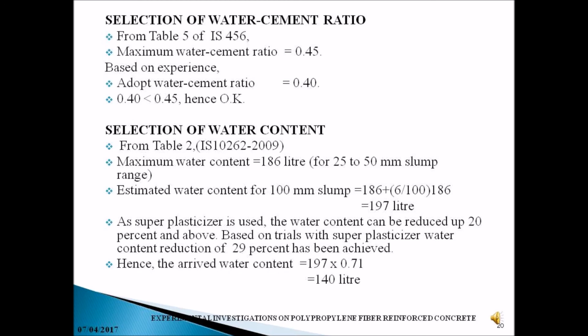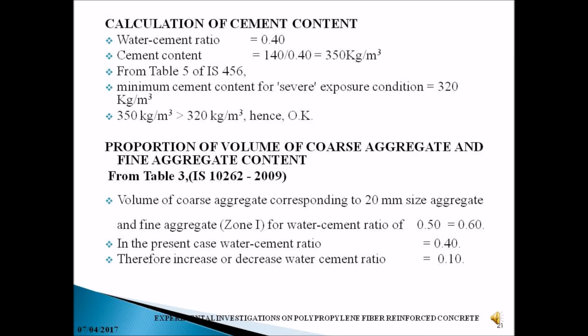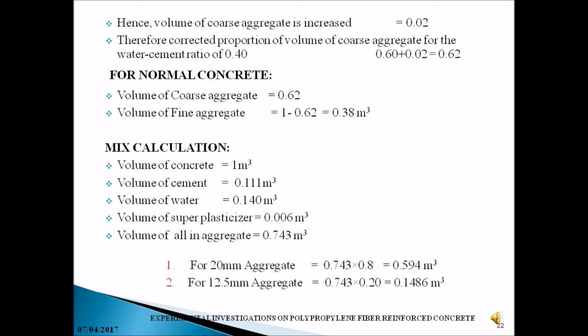Then water cement ratio is selected from table IS 456 2009. Maximum water cement ratio is taken as 0.45. We have adopted 0.40 as water cement ratio, then the water content, then the cement content, followed by proportion of volume of coarse aggregate and fine aggregate content. Finally, after achieving the volume of all aggregates, we have moved into mix calculation. These mix calculations have been done per meter cube.